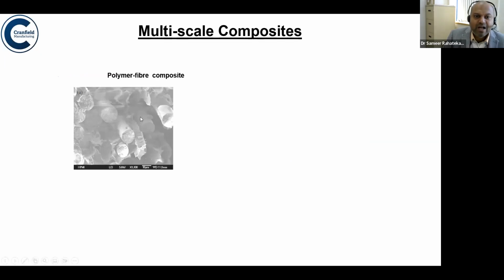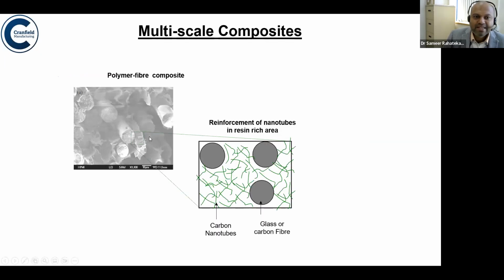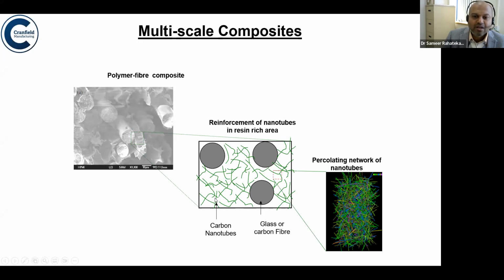So instead of using just carbon fiber and epoxy, as I mentioned before, if you mix epoxy, the glue, with carbon nanotubes or graphene, if there is a crack going between the fibers, the crack will get trapped. Okay, because of the presence of this high stiffness, strong carbon nanotubes, and therefore the crack propagation will not be as quick, and that will increase fracture toughness or reduce the delamination of composites. Okay, this is what carbon nanotubes and graphene after mixing with traditional composites can do to reduce the damage due to crack propagation in composites. So I'm happy to answer the question later on, but this is quite an exciting area.